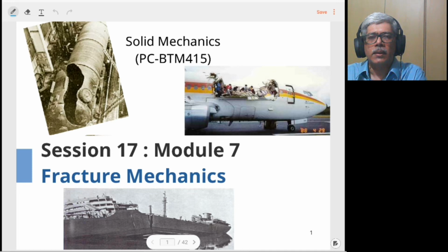The basic equation in this approach is that you have to calculate for your component and crack geometry what is the stress intensity factor and limit it within the material property which is known as the fracture toughness of the material. The stress intensity factor depends on what mode of failure your component is having. So we have seen three modes of failure. The first mode or the opening mode, which is a very widely researched and well documented topic.